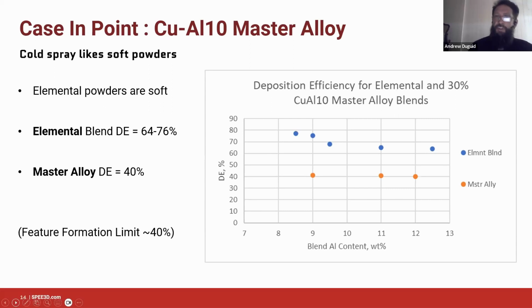And what we can see here is the results of our trial for nickel aluminium bronze. There are two data sets there. The orange one is where we had a combination of some elemental powders and a CuAl10 master alloy. We were at that stage playing around with different blend aluminium contents because we were dialing in our composition. And you can see that the DE for that master alloy blend is a fairly stubborn 40%. Unfortunately for us, that's about the limit of feature formation in our AM process. If you're below 40%, you really can't form the features on the part particularly well. So that wasn't particularly attractive.